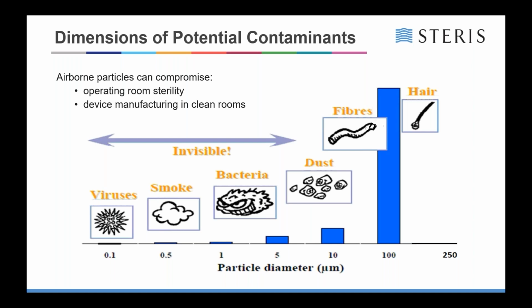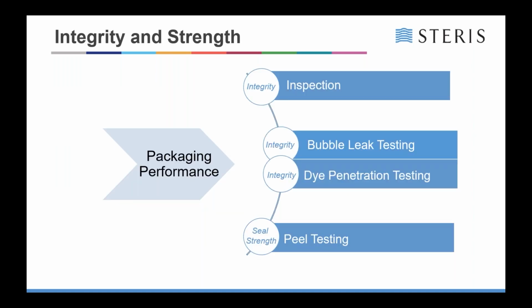You can go a lot lower than that, down as far as maybe 1 micron, depending on the likes of gas sniffer tests and things like that. But again, that's dependent on what's available and what's applicable to your packaging and the materials you're using. The typical test standards normally used for validation in medical devices will be the likes of inspection, so that's a visual inspection, bubble leak testing, dye penetration testing, or peel or seal strength testing.